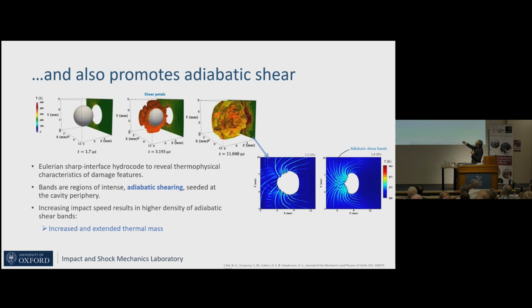And you can see a projection on the back plane of what the temperature is. And as that moves over to the right, this is moving over in time, you can see that these features that we saw in our X-ray radiographs are actually petals. The petals of damage. And they haven't grown out as a spherical envelope of temperature, but they've actually retained their discreteness, their fineness. And the reason for that is because these are adiabatic shear bands. Adiabatic, by definition, means there's not enough time. We are striking the material so fast, not giving it time to dissipate that energy.